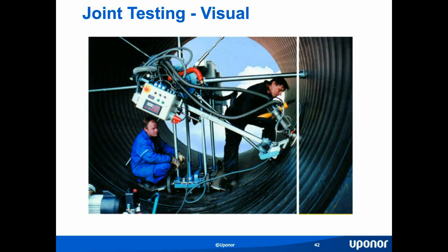It's becoming more and more common for consultants to specify some particular type of joint testing. And on many occasions, we do just state a visual inspection because our techs are very well trained in noticing a joint that may not be correct. They will notice the color of the resin may be off a bit, maybe kind of looking a pale white color, or perhaps even a bit bubbly. That would be from moisture within the resin. And if they see that, they start welding, find the problem, and then grout or route out the old joint and then re-weld it. And that's what happens when we have our visual inspection. We do notice things like this that we can take corrective action on.